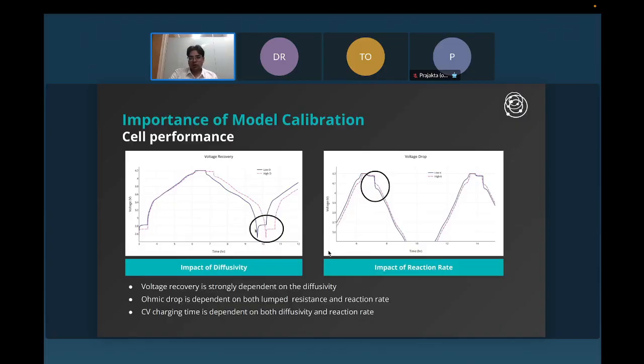And also, what it results in is the amount of recovery that the cell shows once you have fully discharged it and put it to rest. All of these things are tightly governed by the reaction rates at the particle surfaces and the corresponding diffusivity of the particles. And if we have not determined them properly, whatever cycling response we get from our models is never close to the response you would expect the cell to have.